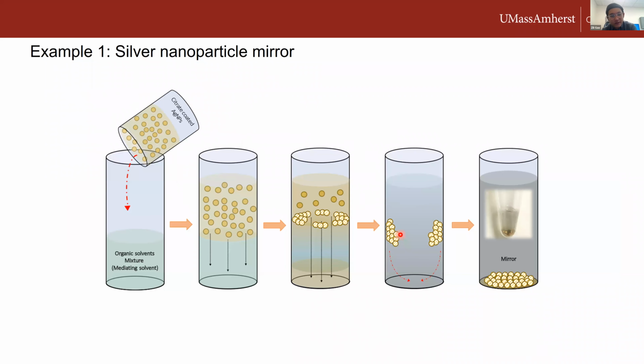So what is a silver mirror? This is a scheme of how to prepare the silver mirror. Actually, the preparation protocol is very simple. In this case, we have our concentrated silver nanoparticles here. We mix them with the mediating solvent, which is an organic solvent mixture. This mediating solvent will adjust the surface charges of our silver nanoparticles, making them aggregate to each other. The aggregated silver nanoparticles will gradually condense or sink into the bottom of the vial, forming a very shiny layer of silver. So we call it a mirror. You can also think of this as a very thin film of aggregated silver nanoparticles.